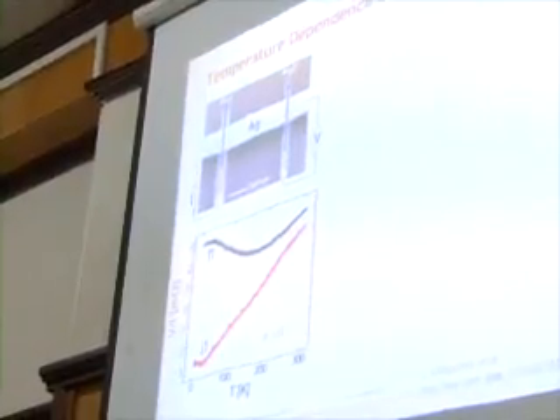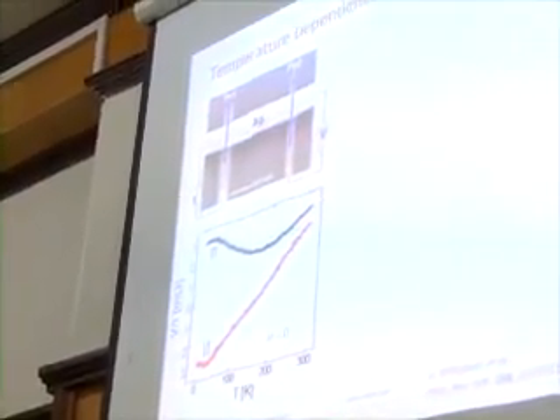Then we change the magnetization of one of the contacts, and something else happened. Well, now we have a voltage here that's negative, and then it just goes up, becomes 0, and then becomes positive at higher temperatures. And you say, whoa, what's happening here? Well, what happens is very simple, actually. At low temperatures, we have indeed switching from a net positive to a net negative voltage, just as I explained to you in the little cartoon picture how a lateral spin valve works.